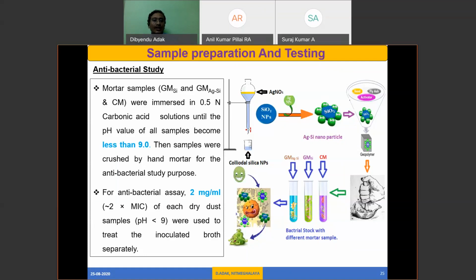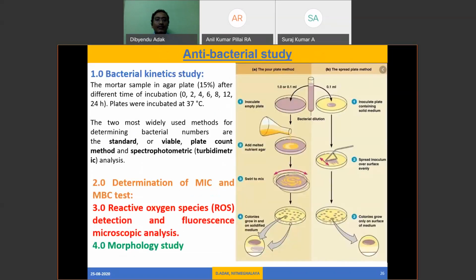So what we have done is prepare the mortar specimens and place them in a 0.5 normal carbonic acid solution for a long duration, until the pH of the solution becomes less than 9. When the pH of the solution is less than 9, we take out the mortar specimens and study the antibacterial property. Now, the antibacterial property is studied with four methods.